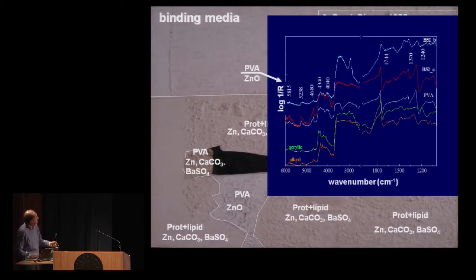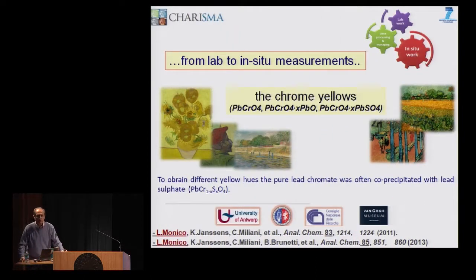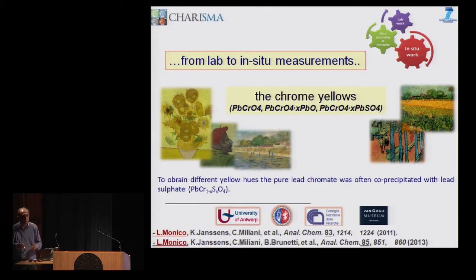And here is the recognition of PVA, which you can see is quite well evidenced, thanks to this band at 1370 cm-1, that is due to the CH3 symmetric bending that is not present in the other binders that are commonly used in this kind of paintings, such as alkyd and acrylic binders. This was PVA, definitely. So what is important to carry out good measurements in situ is the fact that you have to carry out good work in the laboratory. If you go outside without having prepared the mission, sometimes you can risk obtaining unsatisfactory results.